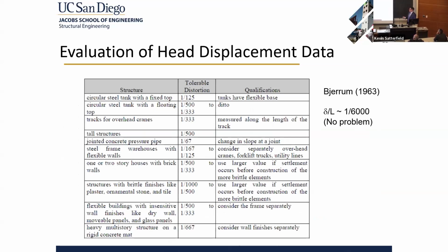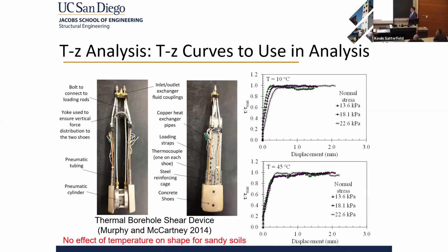Just looking at some different angular distortions from the literature, if one of those was heating and all the rest were not heating, that would be your case where you'd have the most angular distortion. So the change in height over the span between the 2 piles, we were getting 1/6,000. So that's way less than would cause damage to a masonry building. So the amounts of thermal expansion and contraction that we're going to get are pretty small. The stresses induced could be high.